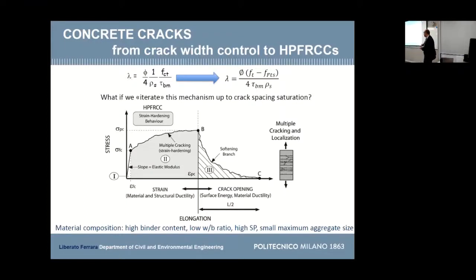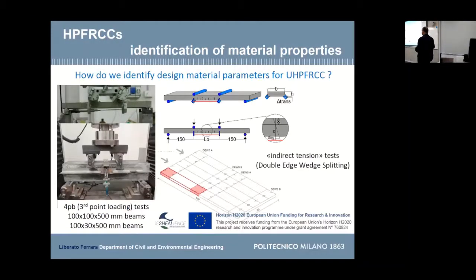And as long as you can form cracks up to crack spacing saturation, you follow this strain hardening, which can be more or less steep depending on your mix design and so on. And you have this multiple cracking and strain hardening capacity. Well, obviously, this depends on binder content, water binder ratio, use of superplasticizer, very small maximum aggregate size, fiber dosage, fiber orientation, several parameters. But this is the basic concept.